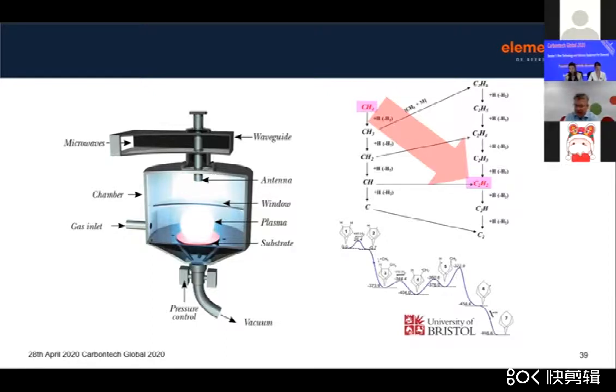I think that the growth of the diamond predominantly comes from the C2. It plays an important role, and I think there's a lot of modelling work around that talks about how the surface plays a role and the chemistry plays a significant role in this. As you can see in the model here, we show the methyl radical as being of high importance, but obviously in the growth process you're also getting an awful lot of the C2 type radical, and that is an important part of the CVD growth process.